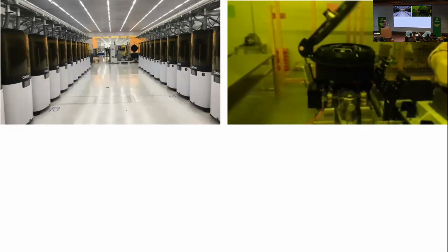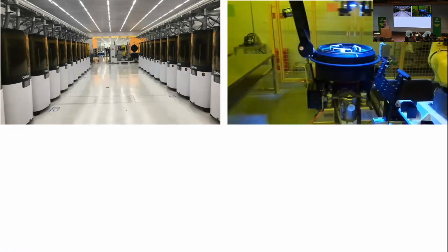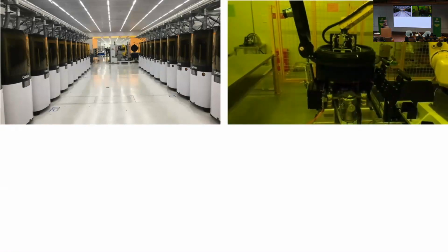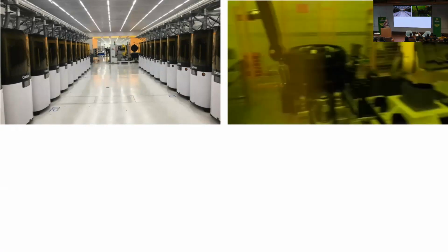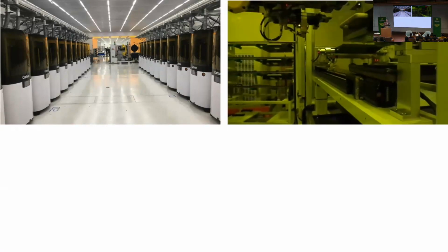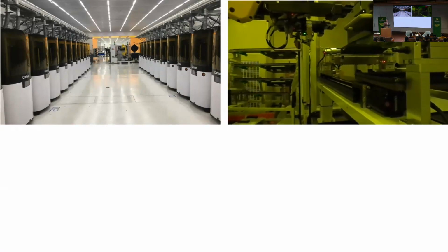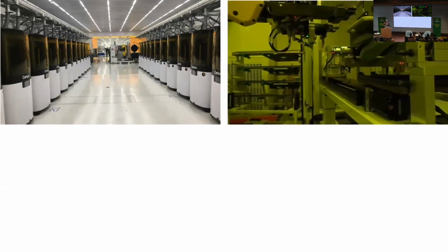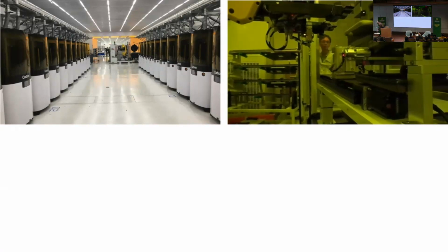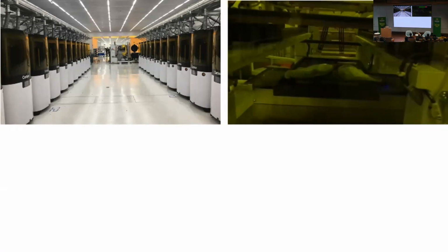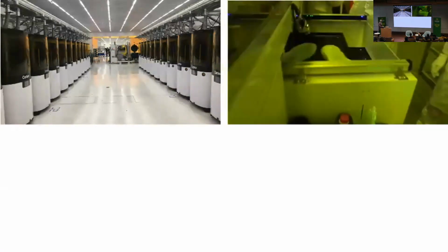This is basically a centrifuge, or a salad spinner, if you will. And you'll see a pair of running shoes on that platform. And when the parts are first printed, there's excess resin on the part. And instead of washing them with organic solvents, which is what you do in the lab, these would get spun. Excess resin would collect at the bottom and go back into the printer. Start passing these parts around. And this is how we scale these things up.